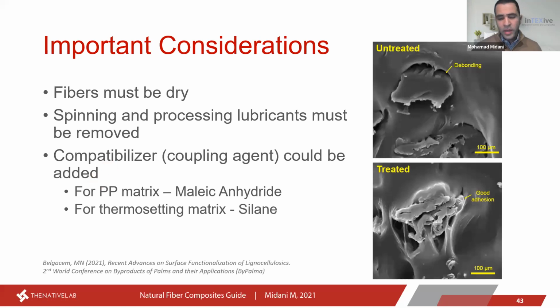And as most of you know, natural fibers are not perfectly compatible with a synthetic polymer matrix. So we need to use coupling agents or compatibilizers to improve this adhesion. The most important coupling agent for polypropylene matrix is maleic anhydride. And in some cases, the polypropylene is sold functionalized with maleic anhydride; it's called maleated polypropylene. For the thermosetting matrix, silane is the widely used coupling agent.